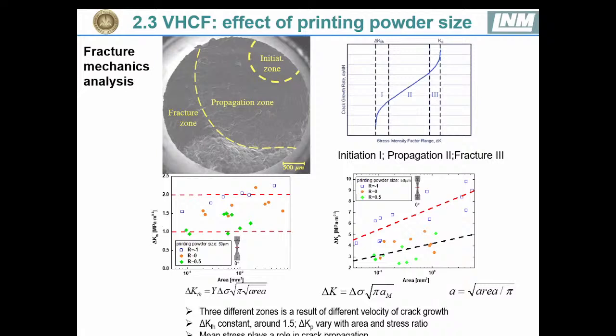Here we calculated, at crack initiation, the threshold of the stress intensity factor magnitude. Here we can see that the threshold at crack initiation is quite constant and corresponds to the threshold of the material, while in the propagation zone the stress intensity factor increases with the crack area, and this means that the mean stress may play a role in crack propagation.